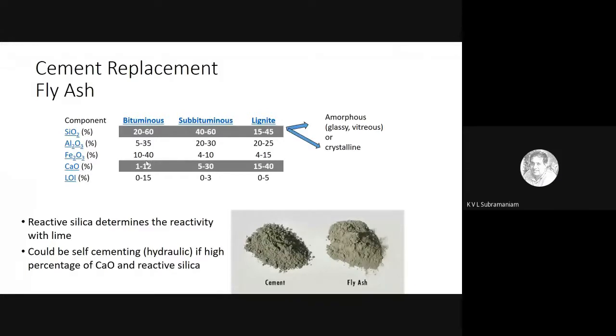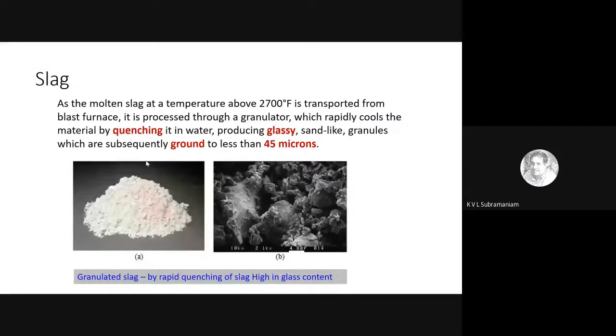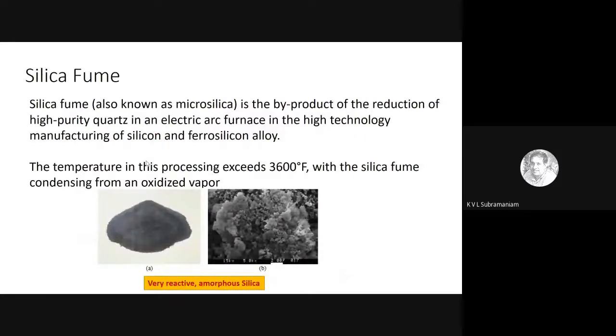cement with this material. Now, slag is another supplementary cementitious material that is made from waste. It is basically the gunk that floats on top of the molten iron. That material is at a very high temperature of 2700 degrees Fahrenheit, about 1500 degrees Celsius, and it is cooled or quenched very quickly to give a glass-like material, which is then ground to a fine size to produce ground granulated blast furnace slag, which we use as a replacement. Again, this is very rich in silica, so it's primarily a source of silica. Then we have silica fume, which is basically a byproduct of reduction of high quality or high purity quartz in an electric arc furnace.